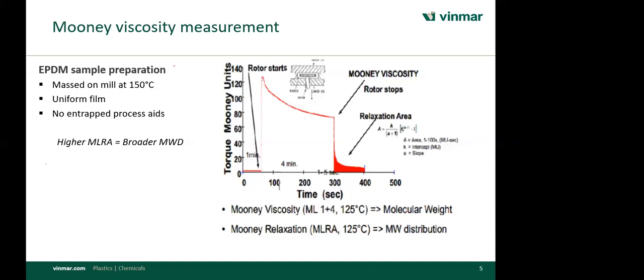So this MLRA is the test. It gives you the percentage of elasticity and viscosity in the molecule. And it is basically a log versus log plot of Mooney versus time. And here you will get the area under the curve. This test is done once your Mooney viscosity is finished. After 4 minutes, you stop the rotor of the Mooney viscometer, and there is a provision for this in your Mooney viscometer instrument. Once you stop the rotor, you start the material to flow on a stress basis, and you plot log Mooney versus log time.